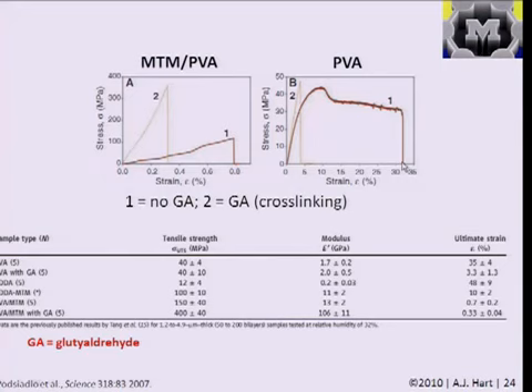By comparison, something like a carbon fiber is a gigapascal or higher. So this is orders of magnitude less than a state-of-the-art composite. But when they make the film with clay plus PVA, and so bond the polymer to the clay and take advantage of the clay properties as well, you see overall the strength is much higher. In this case, the strength is between 100 and 200 megapascals.